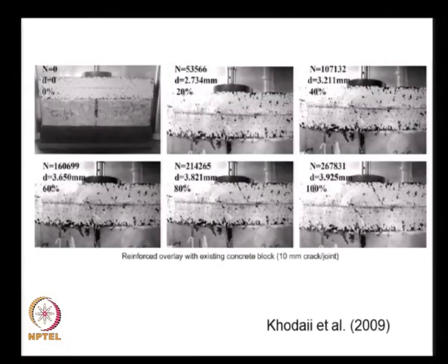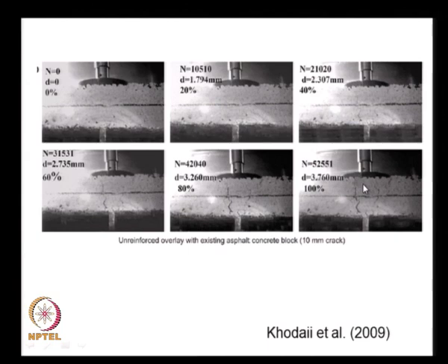Whereas here even at 200,000 cycles the crack has not reached the top, only at about 267,000 cycles the crack has reached the top.